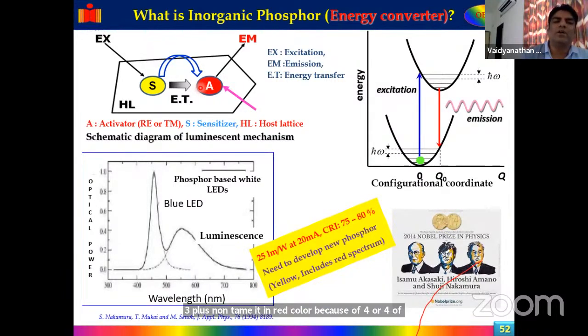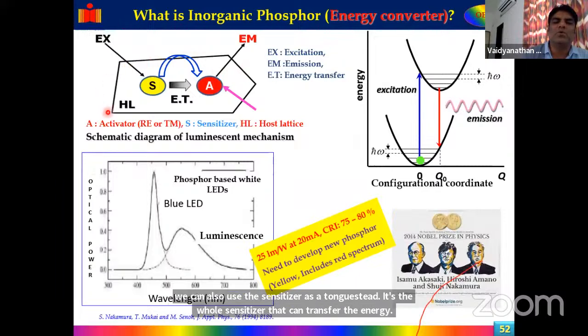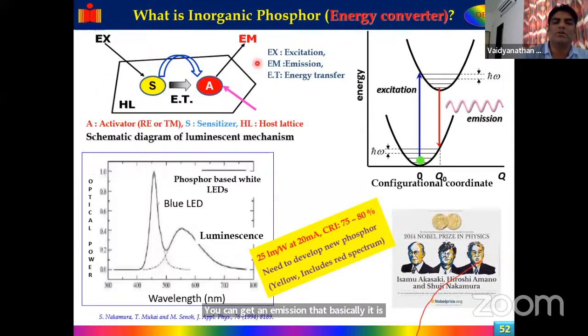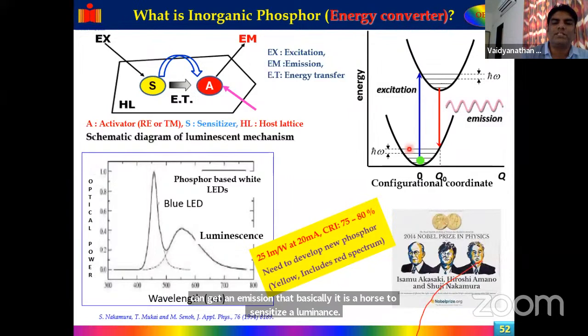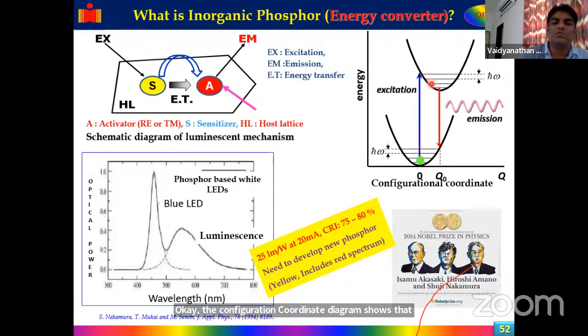So we can also use the tungstate as a sensitizer that can transfer the energy, and you can get an emission. That is basically sensitized luminescence. The configuration coordinate diagram shows that the electron goes to the upper state and comes back to the ground state by emitting a photon.